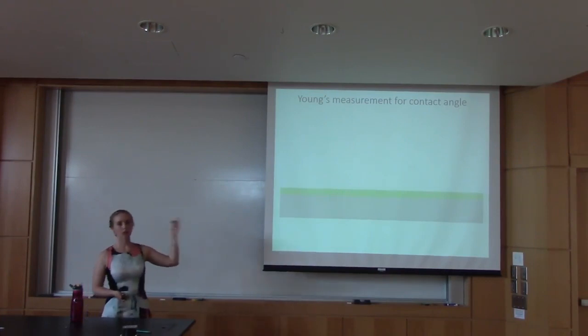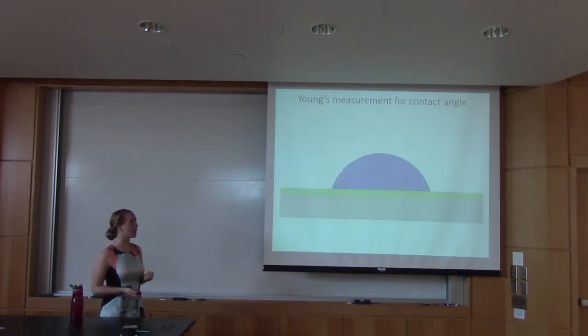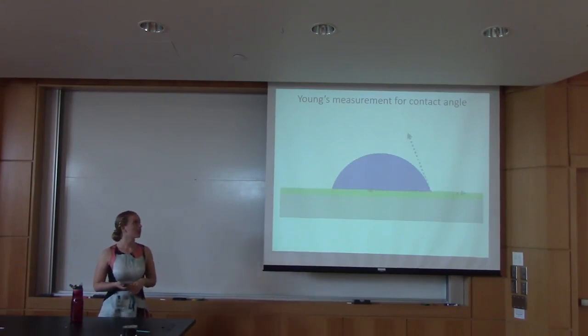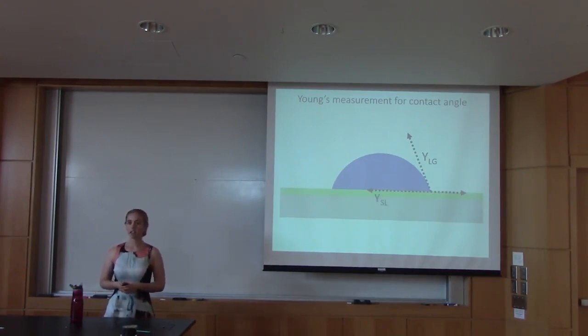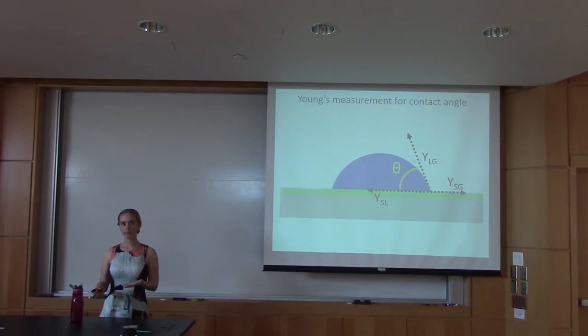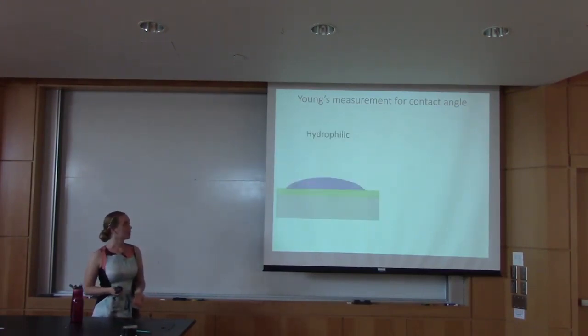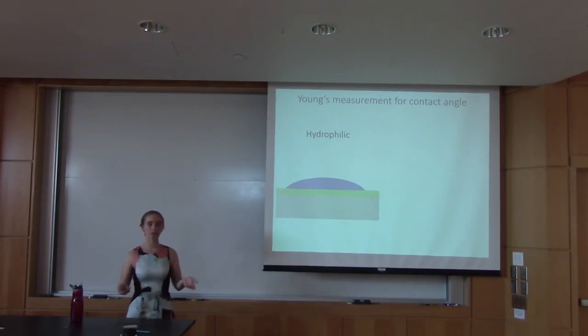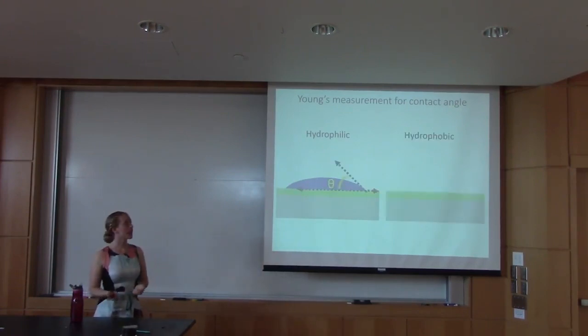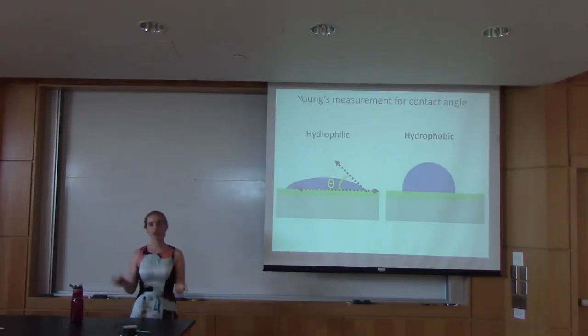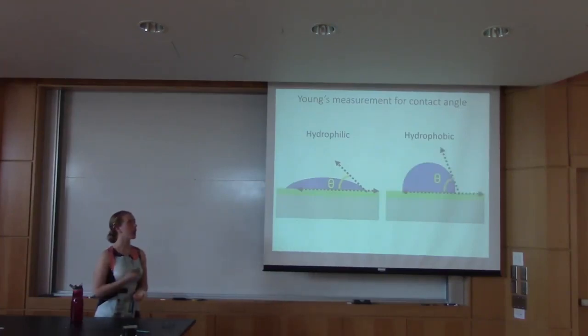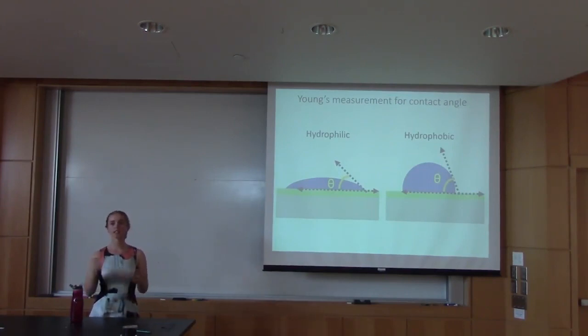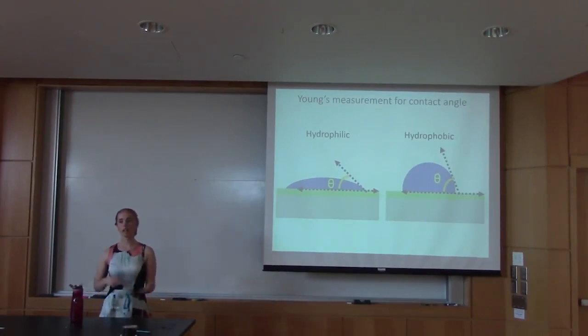So we have our surface, we have our green, which is the random copolymer on top, and then we have this water droplet. From there, we have this intersection, which is the relationship between our surface tension between the liquid and the gas, the surface tension between the solid and the liquid, as well as the surface tension between the solid and the gas. And from there, we have our angle, which is our contact angle. So if we have a hydrophilic surface that has a water droplet that's more broad, we're going to have a smaller contact angle than if we have a hydrophobic surface, which has a much more curved water droplet with a higher surface tension and has a much higher contact angle. So this is how we can tell whether or not a surface is hydrophilic or hydrophobic and to what extent it is.